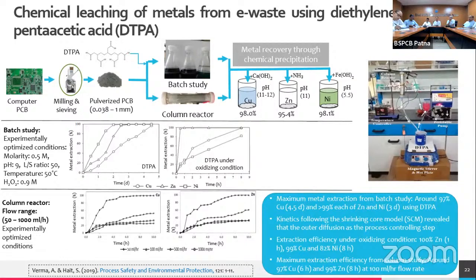And this was not only performed in the laboratory as a batch study; we also have a continuous operation in a column reactor. The batch study has limited utilization of electronic waste. If you use a column reactor, you can use a lot of e-waste, a lot of printed circuit boards. There we also got a similar kind of result. Compared to mineral acid, if you use this organic acid, we get a similar efficiency. The only trade-off is that the time requirement will be more.